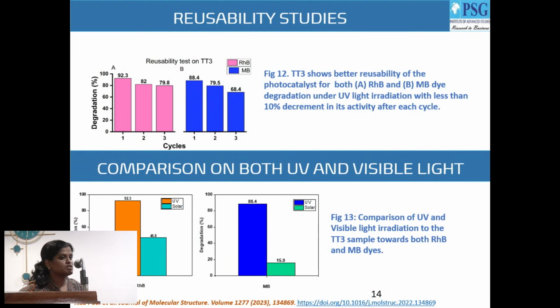So these are the reusability studies we have done for 3 runs. So it shows a decrement of degradation, since we are using the powder samples. After each run we'll be centrifuging, so some of the sample is getting dispersed, so we could find a slight 9% decrease in degradation. Then we have done for both UV and visible light, and since TiO2 is of UV